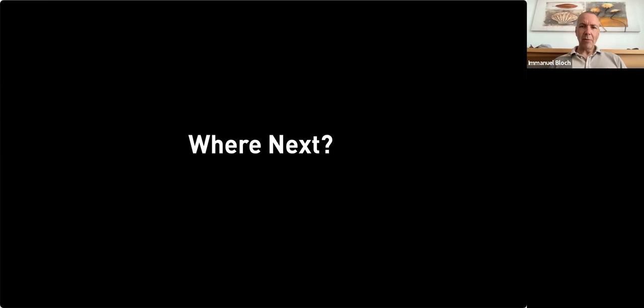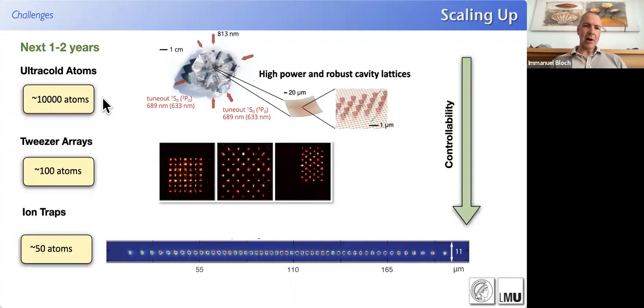All right, just briefly, where do we go next from here? We are right now working hard to scale our systems to even larger systems by making larger laser beams. To make larger laser beams, we have to go to optical cavities because we don't have infinite laser power available. These cavities allow us to use the available laser power much more efficiently to make really very large beams, very large optical crystals. And we hope very soon we can go to system sizes of tens of thousands of particles and study them. And also learn from the ion trap community and the tweezer community to bring this exquisite control we have, for example, in the ion traps to these atoms in optical lattices, combining the large scale of the system with the pristine control levels we have in the smaller systems.